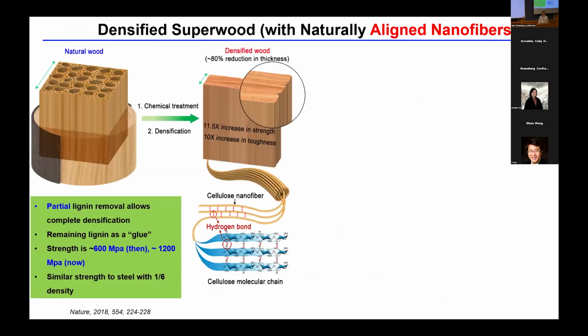At that time, to be honest, we were actually working on transparent wood. But I noticed a sample that had a very weird shape, but it was very strong. So we came to this side, and all of a sudden I felt maybe this is the way to get the strength and get the scale. Obviously, the sample size is pretty big. Now if you look back, the wood is made of fibers, and your task is really to get the fibers together as much as you can, all the fibers inside the entire structure, right? So if you treat it, you soften the wood, and you can densify it. You don't destroy the alignment. So basically, you get what you're supposed to get, right?